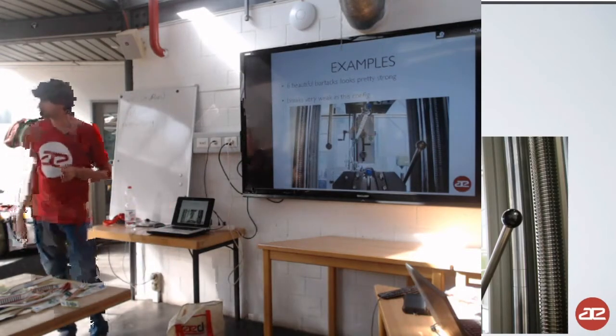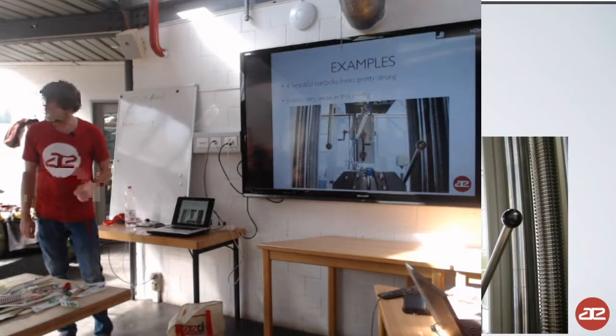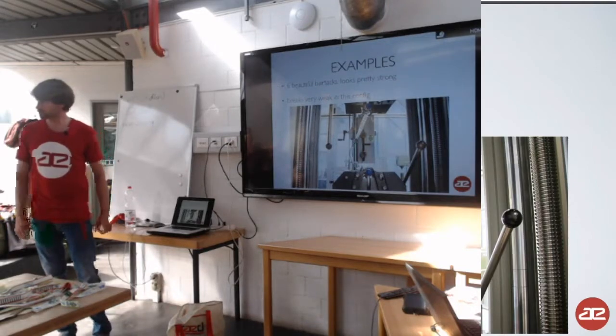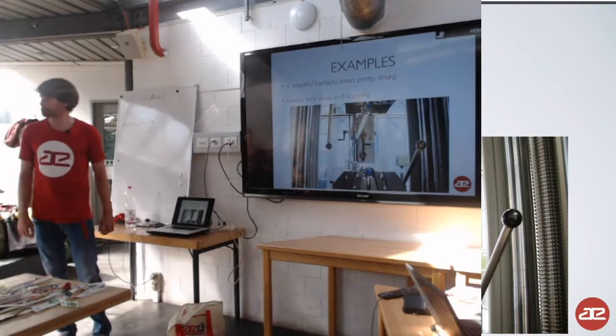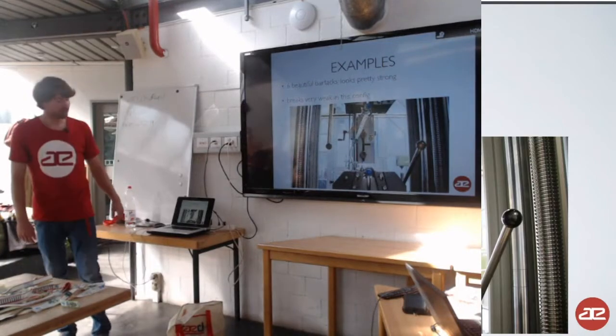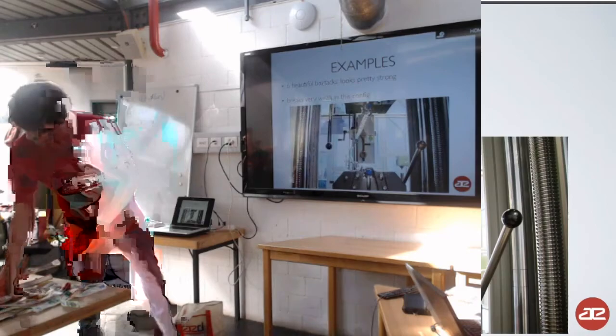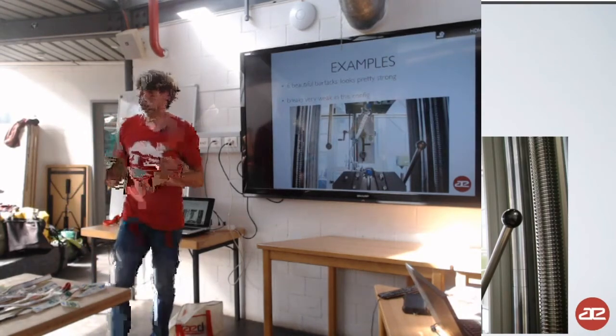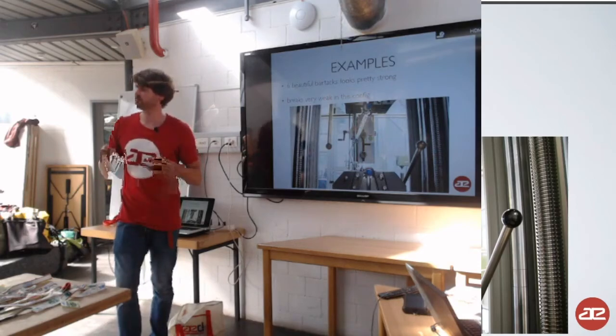I see a bigger one here. I found 5 does break the stitching. 7 does not. 9 gives you this much more, and then it's irrelevant after that. This was 6 bar tacks, and we also went up to 8 bar tacks. What we can find is when we use 8 bar tacks, it breaks the webbing, not the stitches anymore, with the same yarn and the same patterns used. But the point that I want to make with this video: just having bar tacks sewn in does not mean that it's necessarily strong enough that you can safely highline on it.